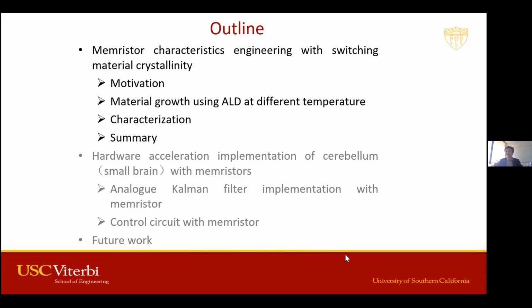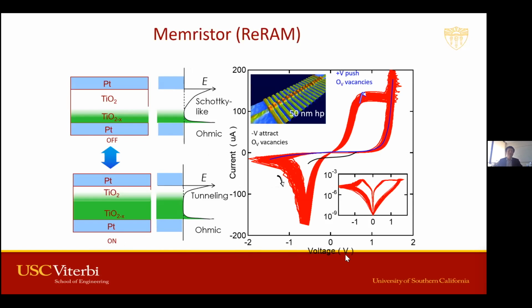So let's talk about the memristor first. Well, a memristor is basically a two terminal device. You have two electrodes, and you have some switching stack sandwiched in between. Within the switching stack, when you apply a voltage high enough, the ions inside move. There are actually several different working mechanisms, and for this specific one, the ions inside the switching stack can move up and down. Because the ions move up and down, they form a conduction channel inside. And then you can have a high resistance state or a low resistance state. And actually, you can not only have a high resistance state and a low resistance state, you can also tune it to have different conductions.